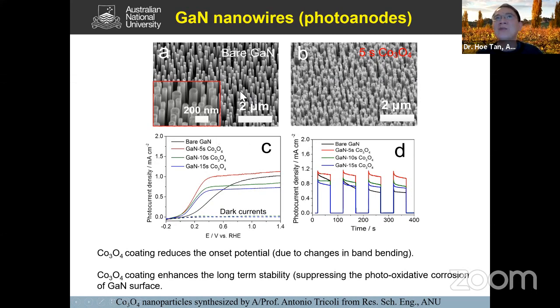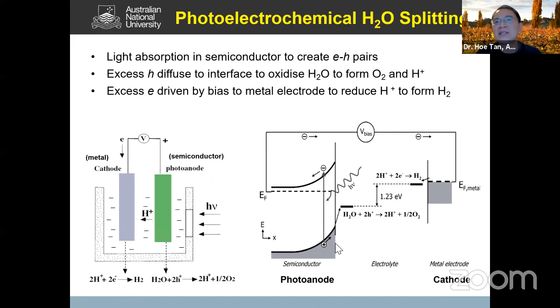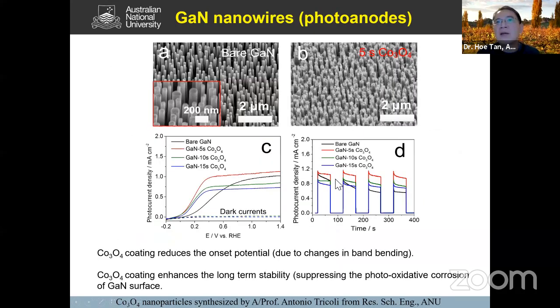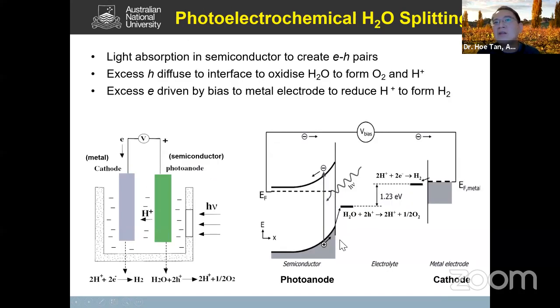But typically in this photoelectrochemical experiment, we also deposit some co-catalysts. Okay, and one of the reasons for co-catalysts is, you know, from a physics point of view, it's very easy to conceptualize that holes can be swept into the electrolyte. Okay, but you know, chemically it's not so easy. So normally what people do is incorporate some co-catalysts, okay, on the surface of the electrode, which is in contact with the electrolyte to assist with the carrier transport.